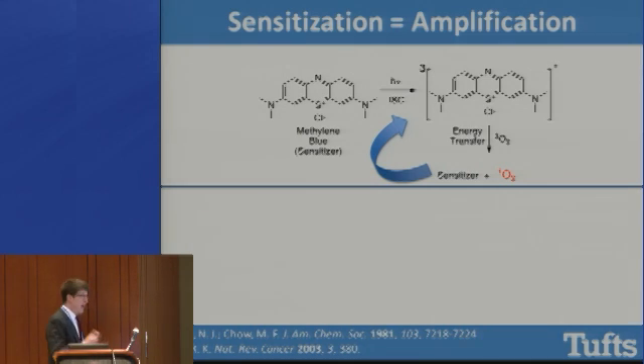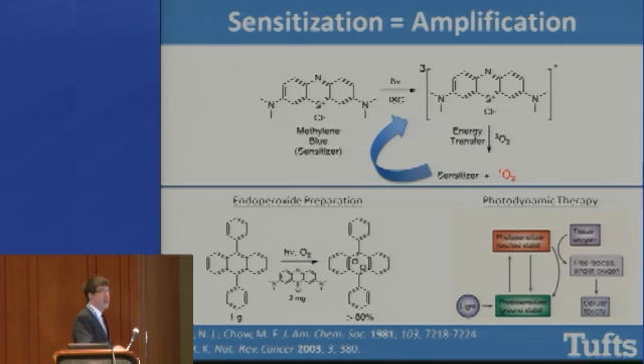And so another thing that we really like about Singlet-Oxygen is the fact that it's chemically amplified with respect to a sensitizer. That is, you can take a sensitizing molecule like this dye, this is methylene blue, and you can do this with a number of different materials or molecules. And upon excitation to a triplet state after intersystem crossing, you get something like a triplet-triplet annihilation energy transfer event, where you basically come back and regenerate the sensitizer in its ground state and produce a molecule of Singlet-Oxygen. And so here the stoichiometric reagents are light and O2, and we can recycle the sensitizer many times. And this is useful in a number of applications, of course, both from a synthetic perspective, so synthesizing things like endoperoxide and products derived thereof, and also in things like photodynamic therapy, where the reactive oxygen species are used for their cytotoxic capabilities.